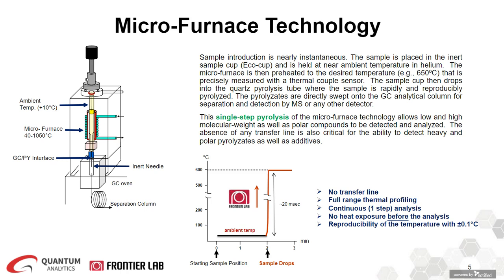With microfurnace technology, sample introduction is nearly instantaneous. The sample is placed in an inert sample cup and is held at near ambient temperature in helium while not subjected to any heat before the analysis starts. The microfurnace is then preheated to the desired temperature that is precisely measured with a thermocouple sensor. The sample cup then drops into the quartz pyrolysis tube where the sample is rapidly and reproducibly pyrolyzed. The pyrolysates are then directly swept onto the GC column for separation and detection by MS. This technology directly deposits all the pyrolysates on column in a single step for a continuous pyrolysis mode. This single-step process allows low and high molecular weight as well as polar compounds to be detected and analyzed.